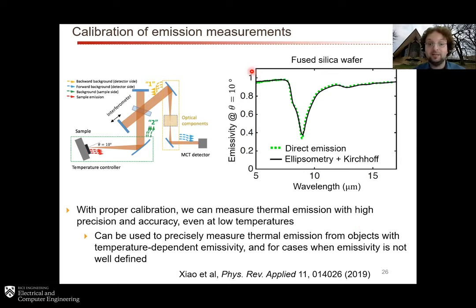So here is a reference. This is the emissivity at an angle. It's the unpolarized emissivity at an angle of 10 degrees versus wavelength of a fused silica wafer. This is one of the references that we like to use to make sure our instrument is working. The dotted lines are the direct emission measurement that I just described to you.